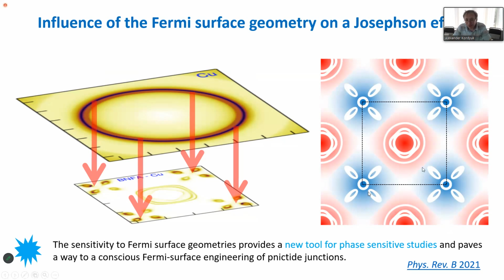But it is important that one sign of the order parameter here is, let's say, plus, and here is minus. And when we have just a junction, when pairs jump from niobium directly to the iron-based superconductor, we have destructive interference. We jump into the plus region to minus, and we have destructive interference. But when we put in between such a filter, the Fermi surface works as a filter, we can cut only some channels, and it is really interesting.